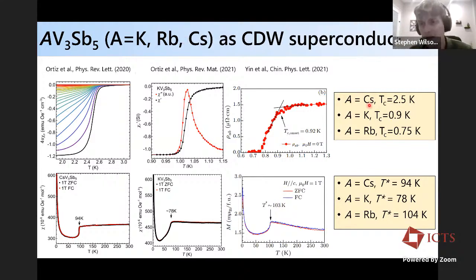Depending on the A site, you get a superconducting transition, which is maximal for cesium at 2.5 Kelvin, and a higher temperature charge density wave instability, which is maximized for rubidium at 104 Kelvin. So you have a much higher charge density wave onset, and out of the charge density wave phase, you see the lower temperature superconductivity onset.